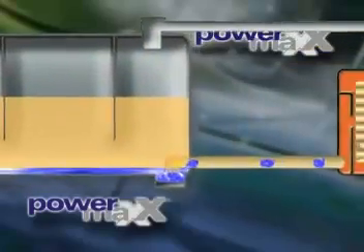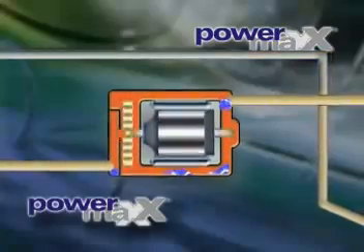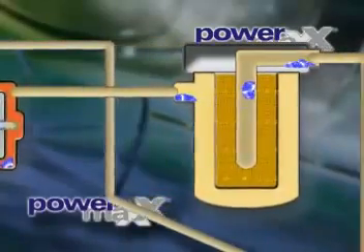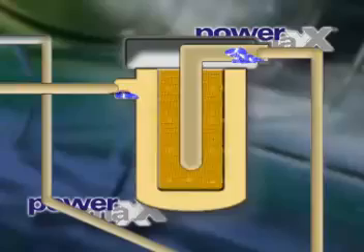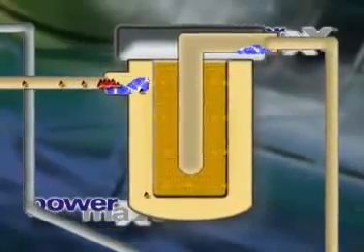Water in the fuel system leads to less lubrication and therefore to higher wear and noise from the fuel pump, to quote just one example. The water triggers a corrosion process in the whole fuel system. Corroded and loose rust particles can reduce the diameter of pipes and do serious damage to the way the fuel system works.